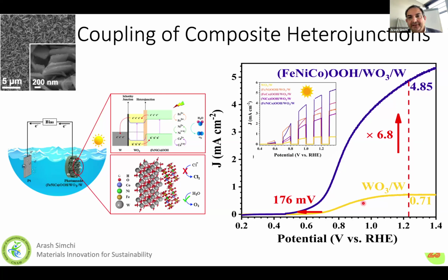And you see here, this is WO3, and this is WO3 with iron, nickel, cobalt hydroxide systems, a multi-layer catalyst. And you see how much we could increase the system. Of course, it's not a perfect one at the moment. The current density is still low, and we need an extra support of energy. However, the concept is very promising, showing how we can use our knowledge of material science to design a multi-layer catalyst structure for better efficiency.